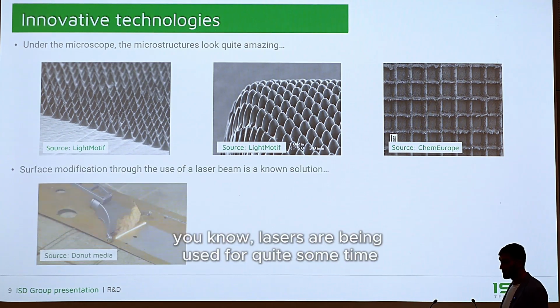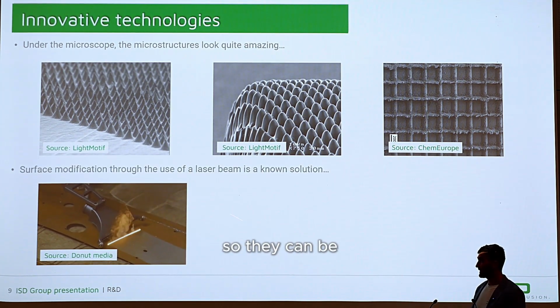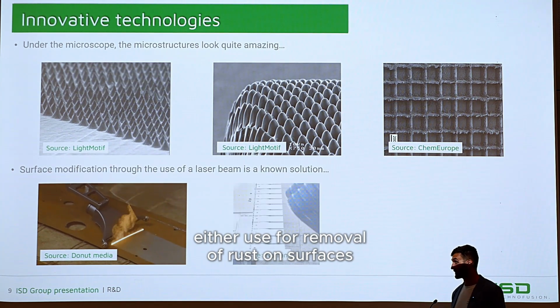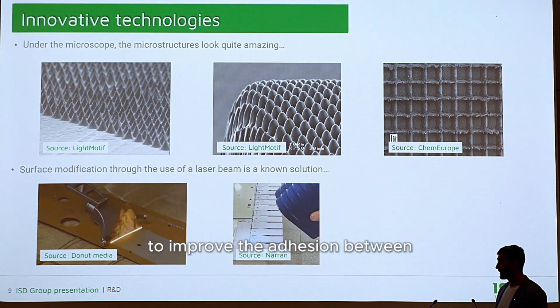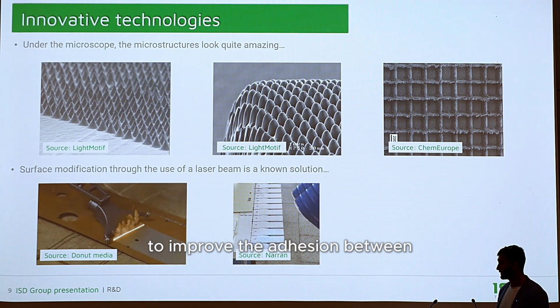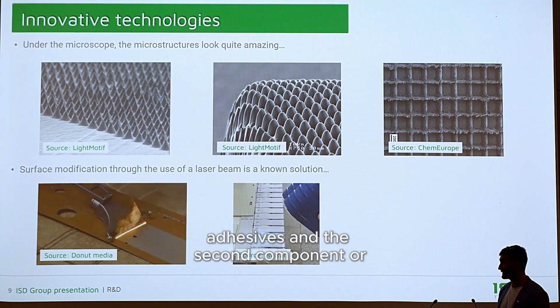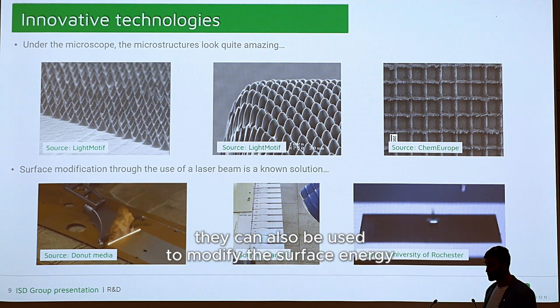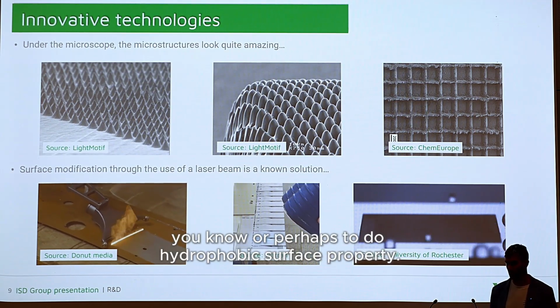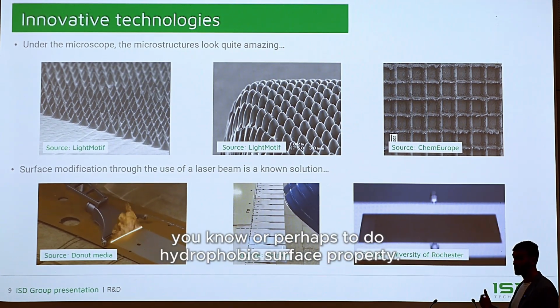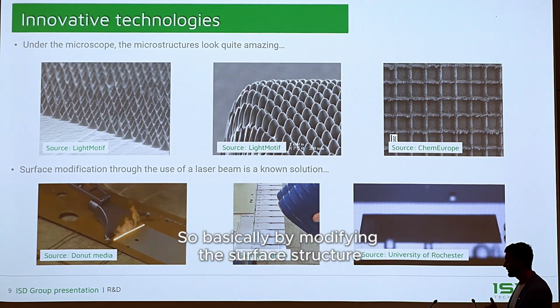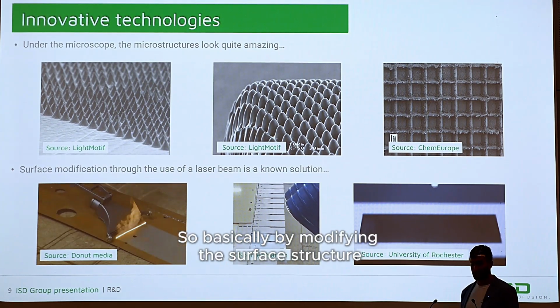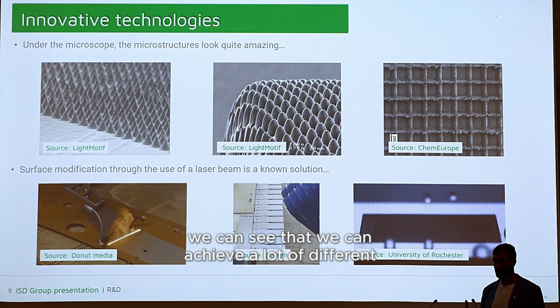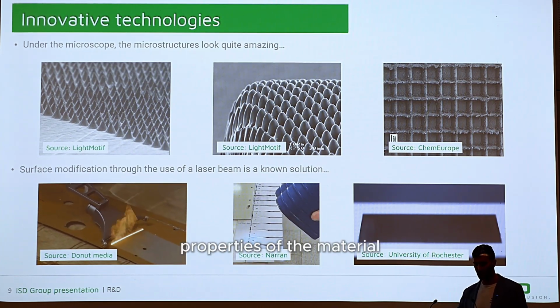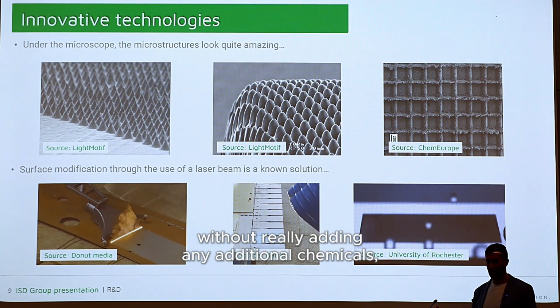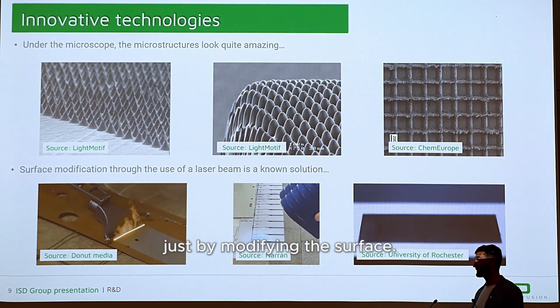The other is that lasers have been used for quite some time. They can be used for removal of rust on surfaces, to improve the adhesion between adhesives and the second component, or to modify the surface energy, or perhaps to create hydrophobic surface properties. So by modifying the surface structure, we can achieve a lot of different material properties without adding any additional chemicals, just by modifying the surface.